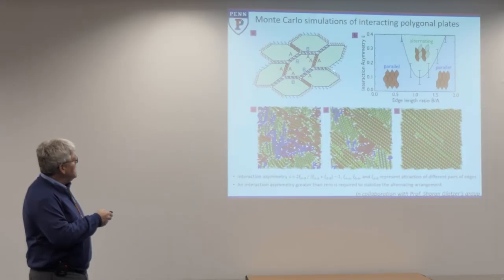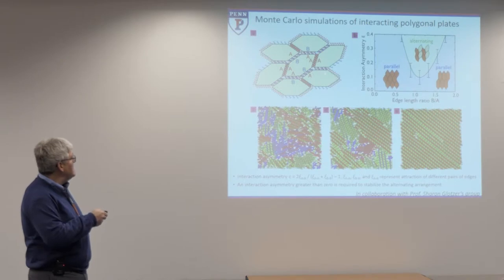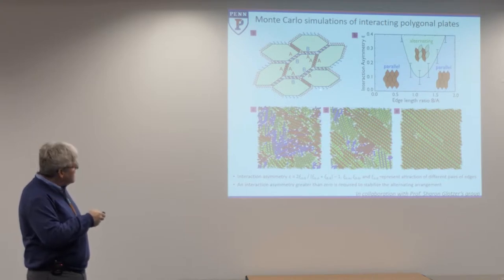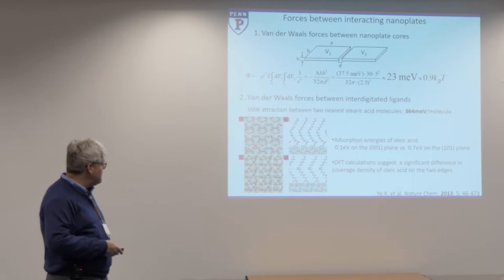And the chemical question was, what is the origin of that difference in strength of bonding in different directions? And so we had chemical analysis that told us what was on the surface, but we couldn't tell what exactly the spatial distribution was. And so in this particular case, DFT calculations helped to encourage our proposal that there should be a difference in the bonding strength and density of ligands on specific facets. And as it turns out, the predictions based on DFT helped to reinforce the idea that there should be one family of planes that should be able to interact more favorably with each other than another set of combinations. And so that predicted difference in the density of ligand binding and therefore the strength of interaction helps to sync up with what we think about for this programming of the organization of the systems.